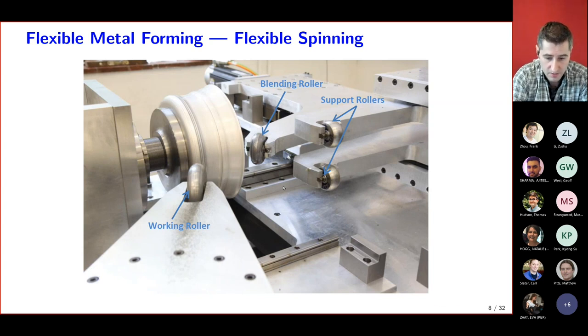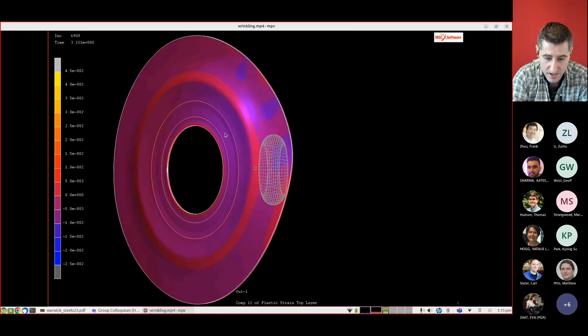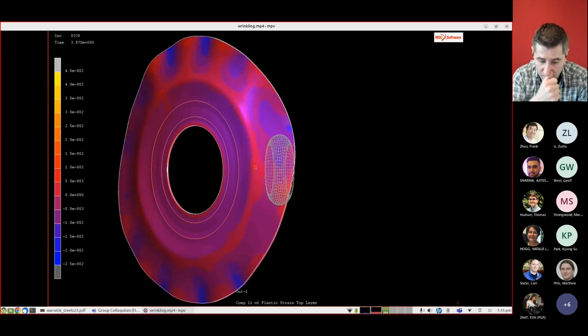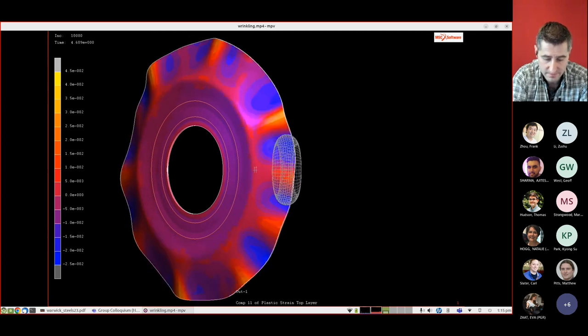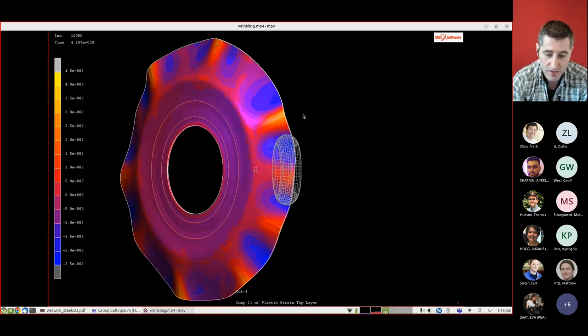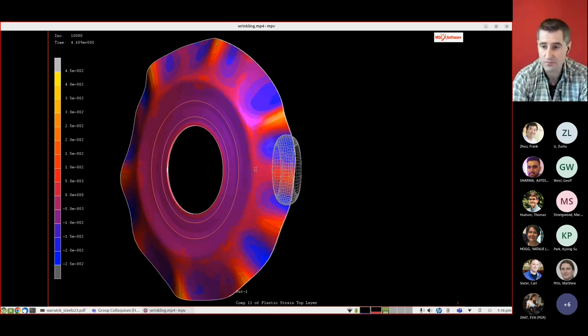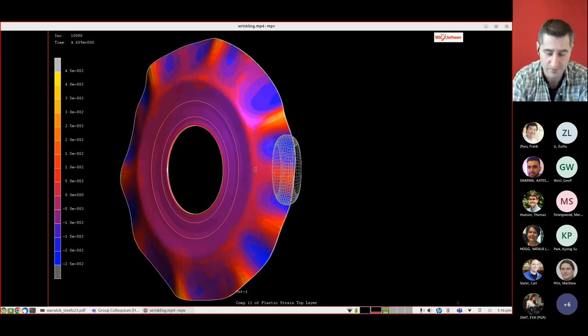One of the problems is that you normally don't go straight to the desired shape in the first pass — you go backwards and forwards, slowly working it. If you're overly aggressive you get wrinkling; if you're not aggressive enough you don't reach the final shape. Here's a computer simulation of wrinkling: a roller pushes on a rotating sheet, and as it gets to the edge, wrinkles start forming, they self-reinforce, and eventually the process has to be stopped. Mathematical modelling could provide a stability analysis to predict whether wrinkling will occur and identify which parameter space to avoid.